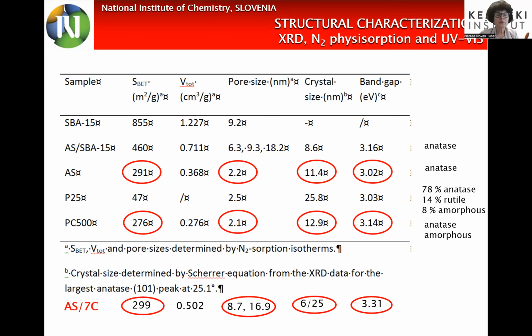So we discovered afterwards that the SBA-15 structure is somehow destroyed, so partly destroyed. So that combination was not very useful, also in terms of the mechanical stability of the coating. But if we look at colloidal titania in comparison with other commercially available titania, P25 and PC500, we can see that we have very similar